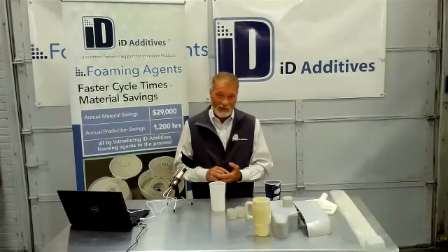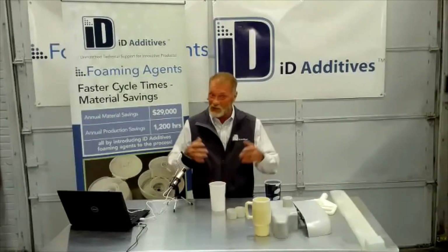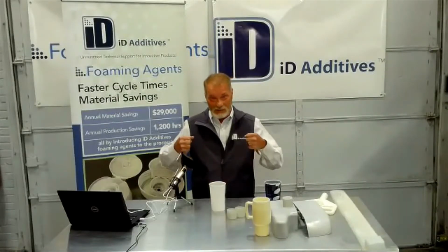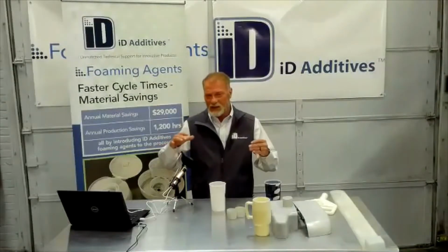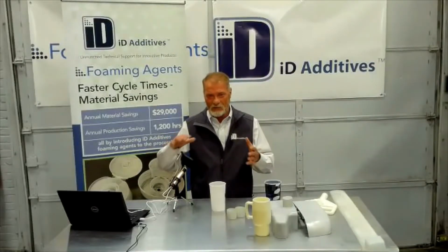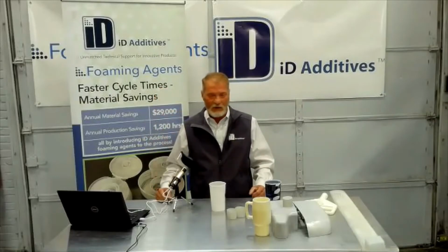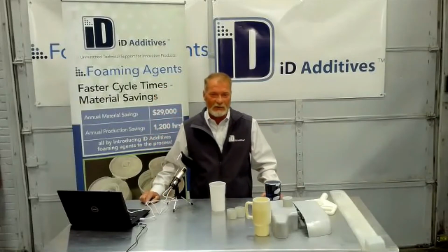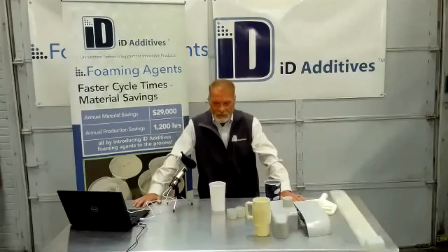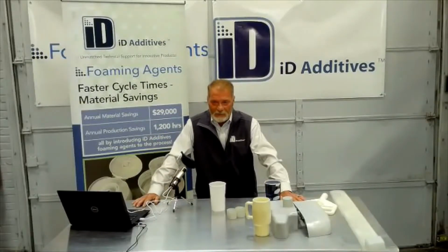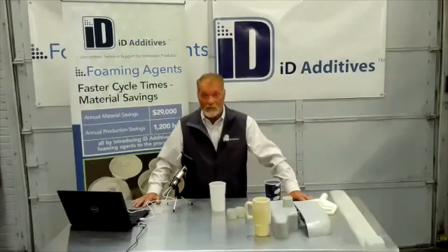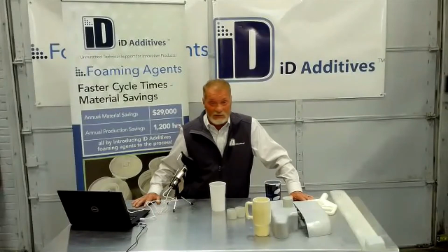I would not use an exothermic in injection molding because you want to pull heat out, and an exothermic is adding heat. It's also tough to control that bubble when you get it all at once. So I never recommend an exothermic in injection molding. Not that I haven't used one. There are very few applications that would do a good job with an exothermic. We do have endos and exos for any application you might have.